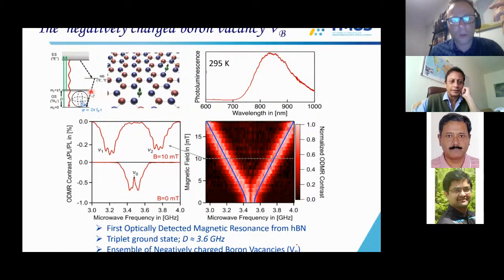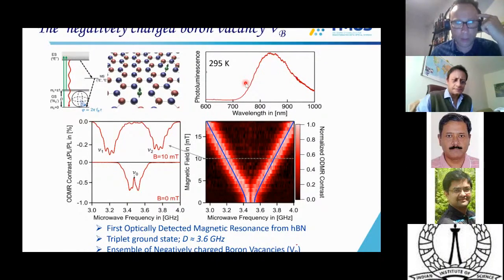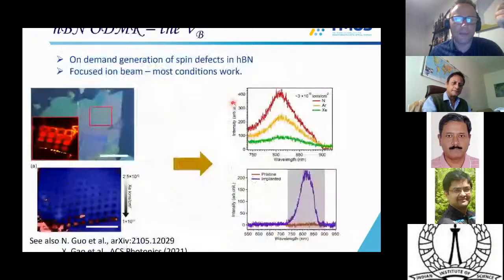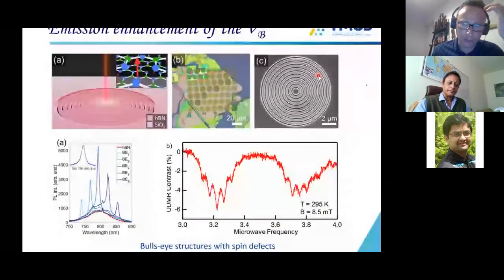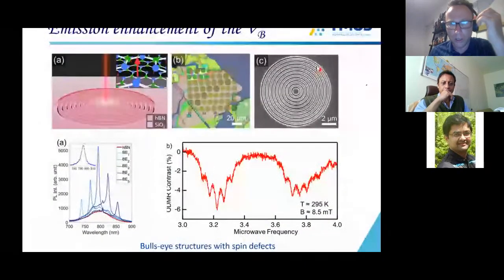Now, how is it related to the bullseye? The problem with this particular system is that it's very dim. The emission here looks good in terms of signal to noise ratio, but it's actually very dim and we cannot get to a single-emitter level. So we were thinking of how to enhance this emission, and to enhance an emission, you need to make a cavity. The simplest cavity is a bullseye structure, which will give you a factor of 10 in emission.